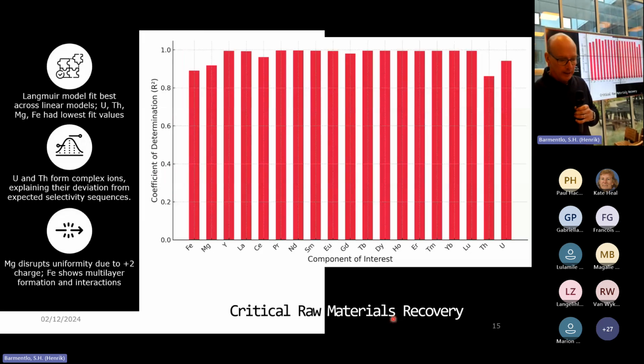How good was our modeling? And what's important is that iron and magnesium were not that good. Our modeling was pretty poor, but we think those are the lower value products, so we're not too worried about whether we're modeling them particularly accurately or not. What we were getting was very good modeling accuracy on things like yttrium and cerium, praseodymium, neodymium. These are the valuable compounds. So we want to make sure we're modeling these correctly in the context of this multi-component mixture.